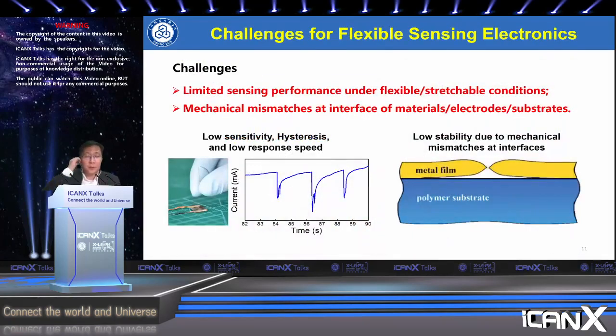Even with the bright future, there are still many challenges for flexible sensing electronics. For example, they have limited sensing performance, usually under flexible or stretchable conditions, because they usually require a flexible or stretchable substrate. It sometimes causes poor sensitivity, response time, and recovery time, and also hysteresis. Another very important issue is that they usually have low stability due to the mechanical mismatch at the interface of the materials, the electrode, and the substrate. So it's a very important thing when flexible sensing electronics go to applications.